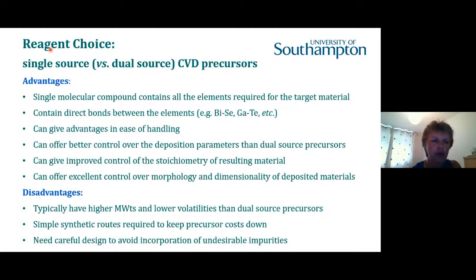So I'm referring here to using our chemistry to develop single source CVD precursors. And what I mean by that is single molecular species that will incorporate the elements that we want to put into our deposited material, our metal chalcogenide material. These elements would all be contained within that single molecular entity. So we only need to use one metal compound for the deposition, but we've got to obviously design that carefully so that we can move it into the hot zone and drive the deposition process so that we achieve the level of control that we're looking for in our thin film material.